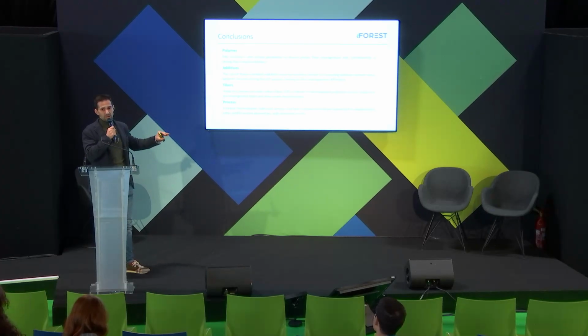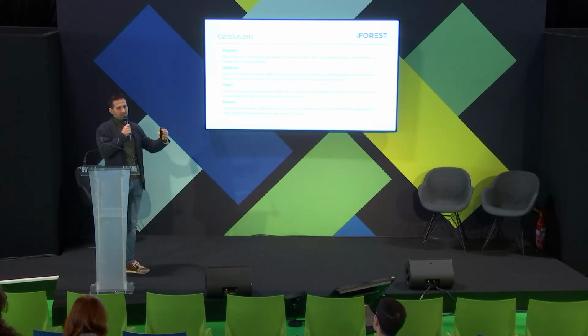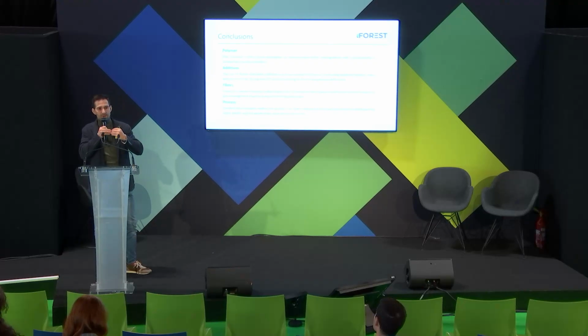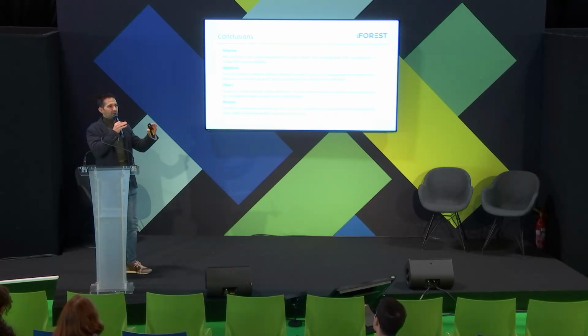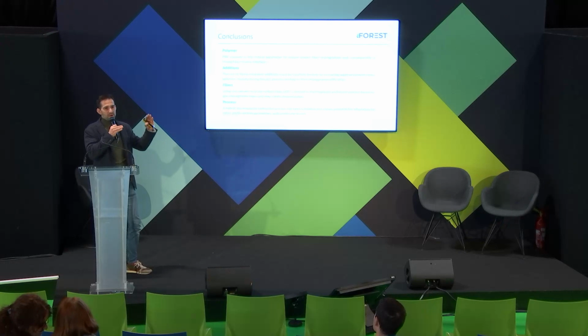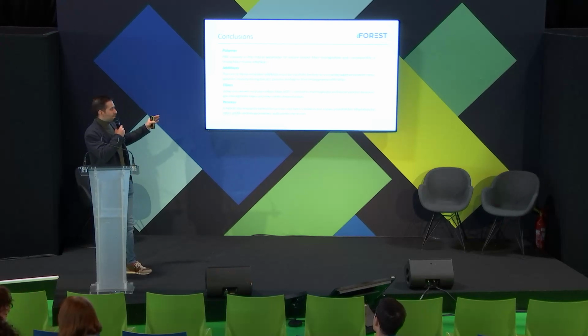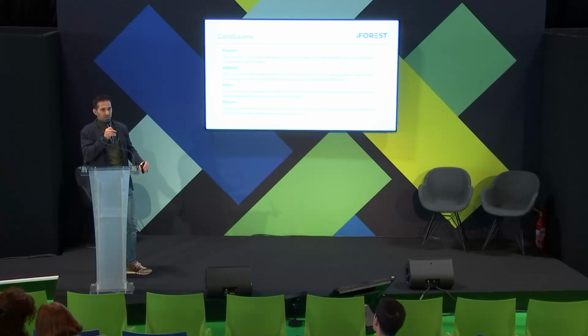We did several trials. If we try to increase the ratio of non-woven in the composite, we have these problems. We have some discontinuities. Sometimes it tears apart inside of the mold. So it's something that cannot be controlled. So non-woven is not made for pultrusion. We achieved some laminates limiting this, with a good ratio between fibers, non-woven and thermoplastic. But it's something that we have to take into account.